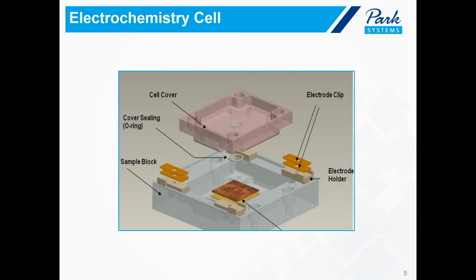The working electrode that was used here in our experiment is a gold thin film. It is about, I think, 150 nanometers thick, and it is evaporated on a mica surface, while the reference electrode and the counter electrode, as I mentioned earlier, are silver chloride and platinum iridium. The three electrodes were connected to a Solartron Modulab XM ECS potentiostat. This is the model of the potentiostat that we use in the experiment.